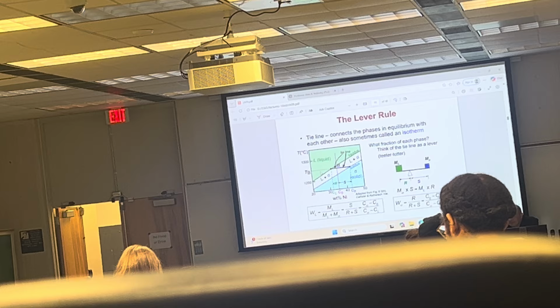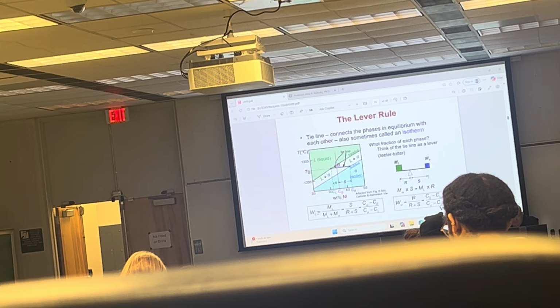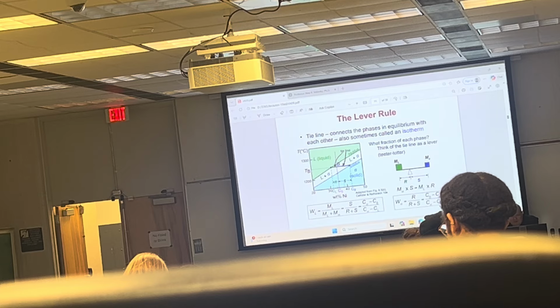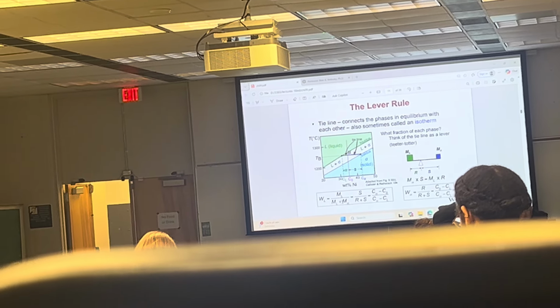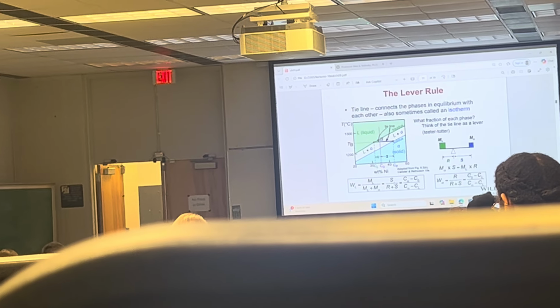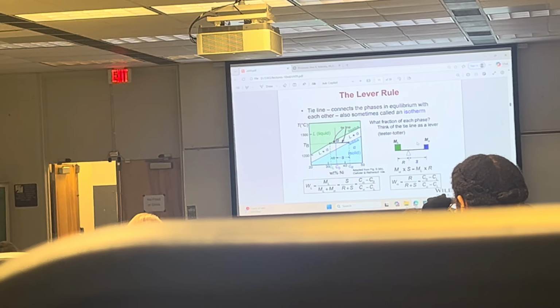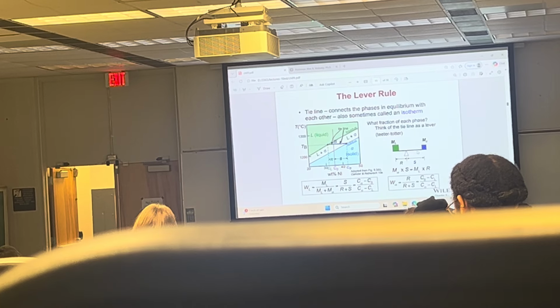The same. And here's the equation for how you would calculate the weight fraction of the liquid phase, which is equal to m_L divided by m_L plus m_alpha, or it's equal to S divided by R plus S. So it's equal to this divided by the whole thing.